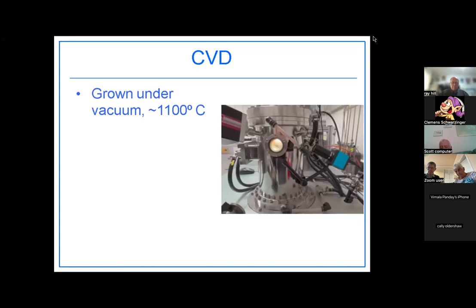All right, and what they'll do is they'll put up to 30 seeds in a single chamber. And under chemical vapor deposition, you could deposit about 100 microns in depth per hour. Obviously, the faster growing rate, you get more inclusions, but they can go as slow as 0.1 microns per hour. So this can take some time for these diamonds to grow.